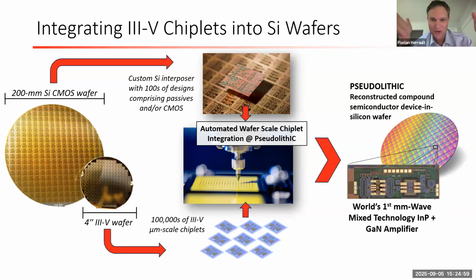The silicon CMOS wafers today are cored down. We are not yet processing at 200 millimeter, though that is very much on the roadmap. So we core those down into smaller coupons or smaller wafers to be able to process them at a shared facility. And we create the cavities and do the reconstruction of the wafer followed by the interconnect. So we're able to mix and match different technologies again. I'm just showing one 4-inch source wafer, but we have a library of technologies, from indium phosphide to gallium nitride and gallium arsenide, available to take from.